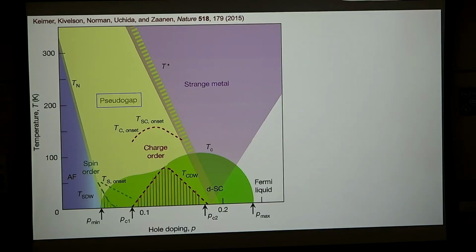It was initially discovered by NMR measurements of the magnetic susceptibility. So if you lower the temperature in any kind of metallic state, you get a Pauli susceptibility, and that's what happens down here. If you come down this way, the susceptibility is roughly constant. But when you're over here, around this temperature T star, it starts to go down.